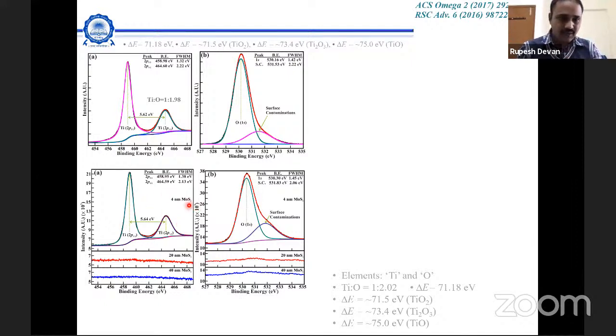When we had a 4 nanometer MoS2 layer on TiO2, the signal comes out, and that gives the information that TiO2 remains in its original form, 1:2. But once we moved to the thicker layer, the TiO2 signal was lost. The question is, TiO2 having the oxygen layer over there, when you put MoS2 on it, then Mo may get oxidized, but we have not observed any oxidation signal over here. That indicates that the MoS2 is synthesized as it is, which is true.